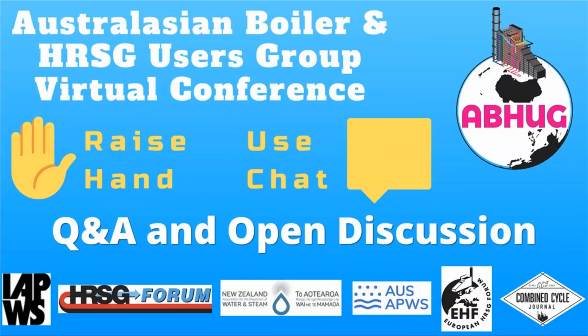For quite a number of years at the ABHUG meetings, we've talked about oxides and temperatures of superheater and reheater tubes, and we call it OGE, oxide growth and exfoliation. And we're trying to take a little bit of a proactive approach, because in brief, don't wait until you see the situation that you showed with massive amounts of exfoliation on the outside. We're trying to take the same approach that we took with the HP evaporators, in terms of removing those and looking at the internal deposits so that we can stop failures from taking place. And that's exactly what we want to do here for superheaters and reheaters.